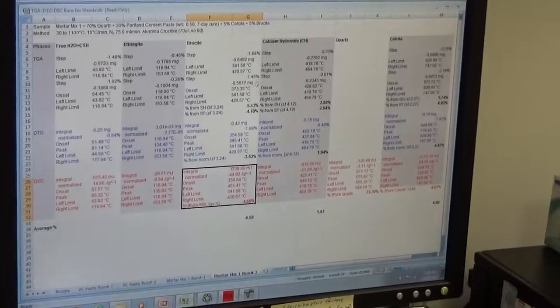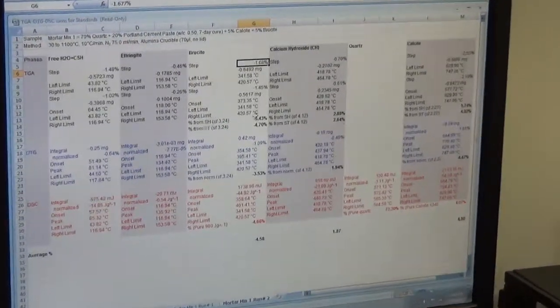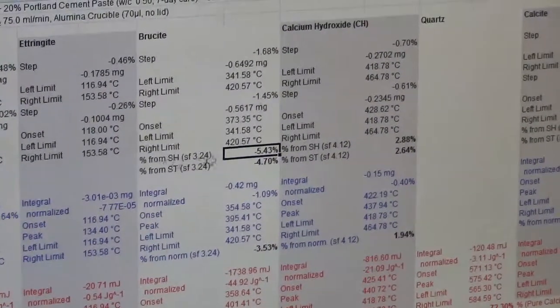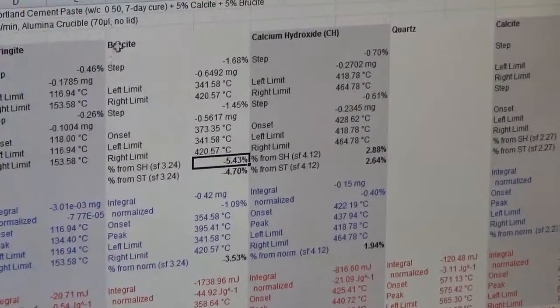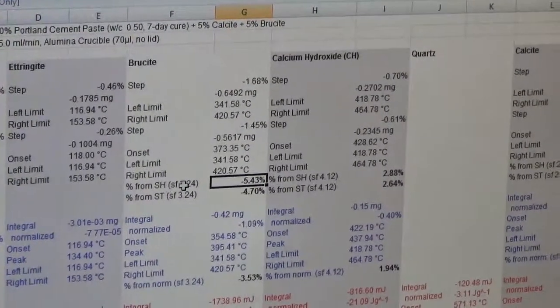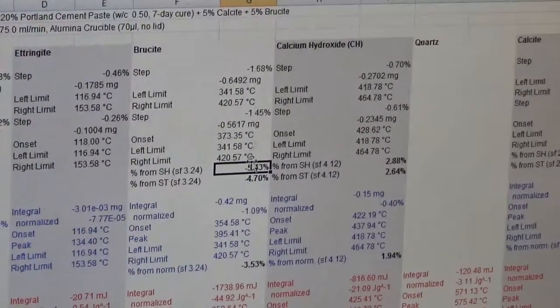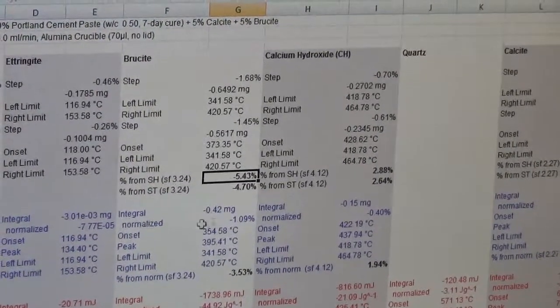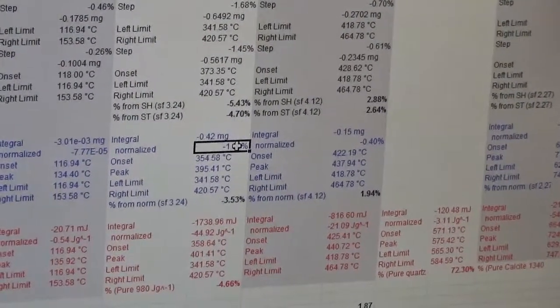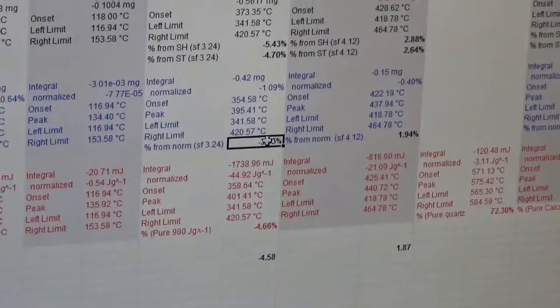To calculate the actual brucite content from the weight loss: this is the percent loss in weight. To calculate it, you simply multiply that by a factor of 3.24, which is the stoichiometric factor for brucite dehydration — basically the ratio of the molecular weight of brucite to the molecular weight of water and MgO. You multiply that factor by the percent loss in weight and you get the brucite content.